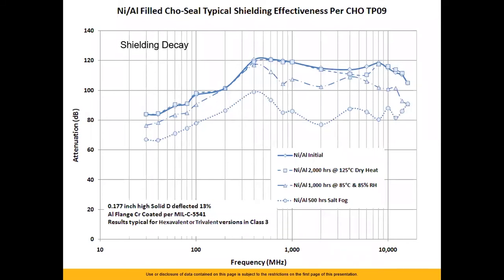So this is a typical shielding curve run on a pretty standard mil spec test, a solid D extrusion tested for EMI shielding. And you notice the top curve is the nickel aluminum by itself, not run through any kind of testing. And then we take it and we run it through a 2000 hour, 125C dry heat. We do 1000 hours at 85, humidity and temperature, and also the 500 hours salt fog. So you can see the curve, actually the shielding decays and lessens over time. So corrosion really affects your ability in the field to resist susceptibility and also not radiate its own EMI interfering with other electronics around. So it's very important to realize that yes, you designed it perfectly, but over time you will see some shielding decay.